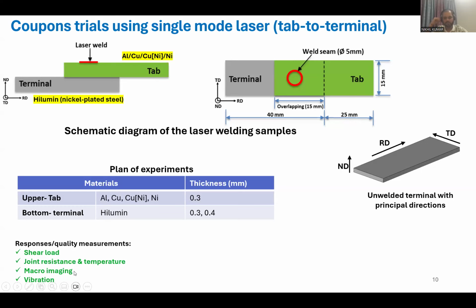If you melt the bottom sheet 100%, you will end up cutting, not welding, and you are going to have electrolyte leaking, because you have to implement those parameters on the battery, and the battery is a closed casing. There is electrolyte filled inside, so you don't want to penetrate those cans 100%. So the micro imaging is very important after welding, before going to the final weld.